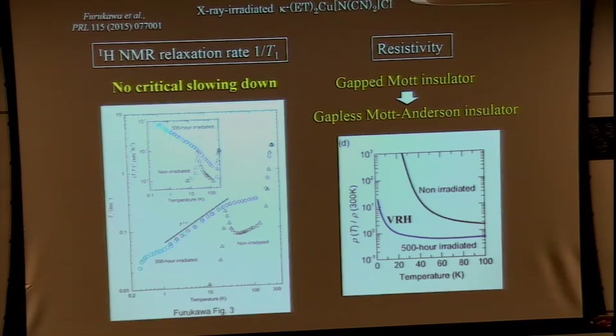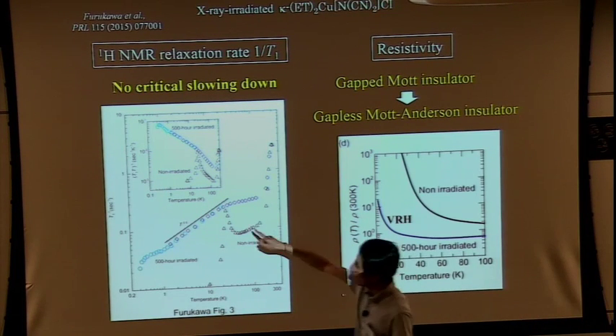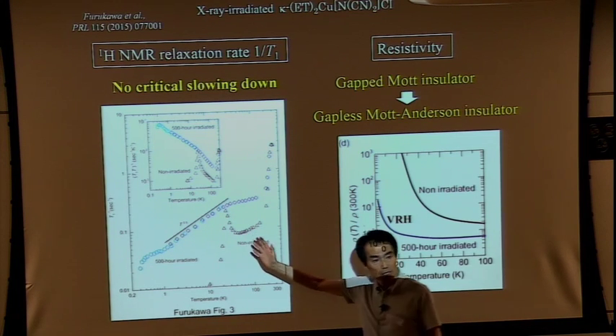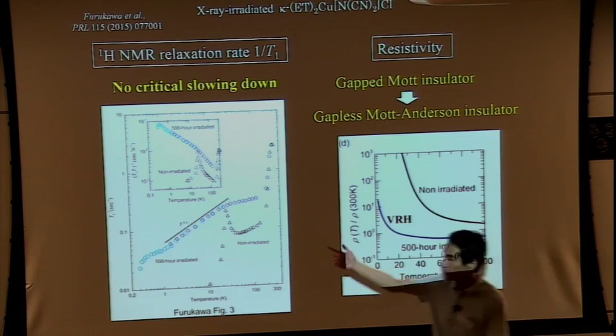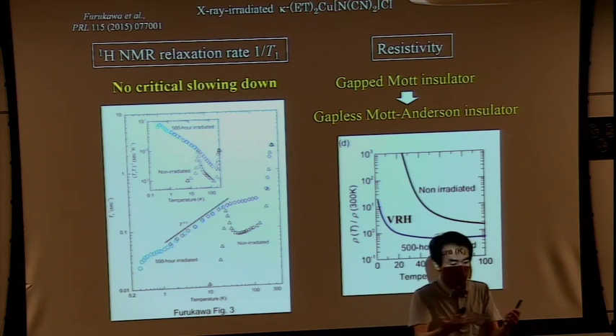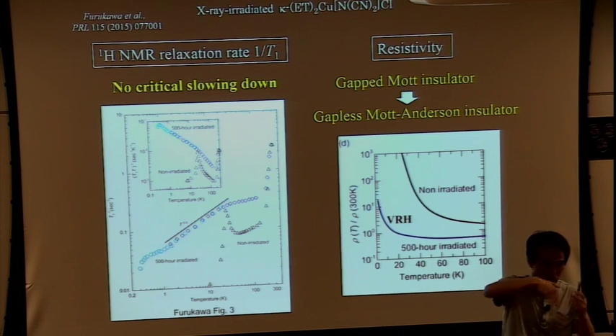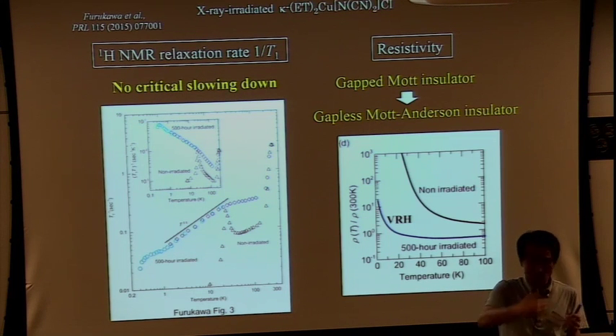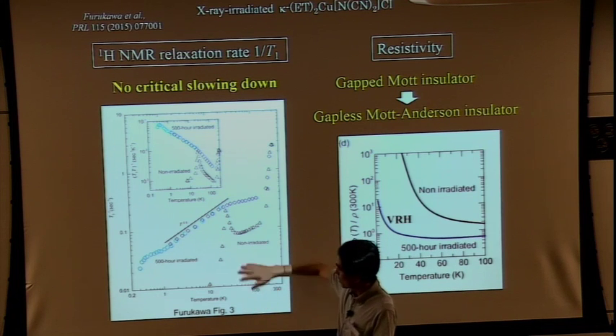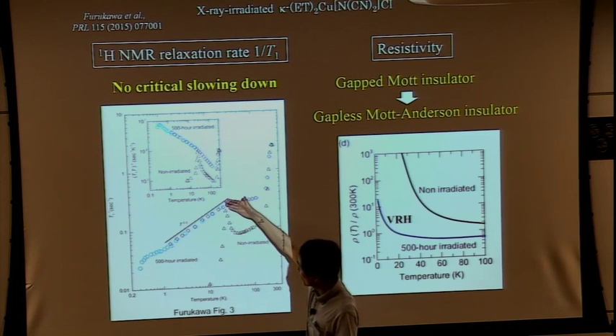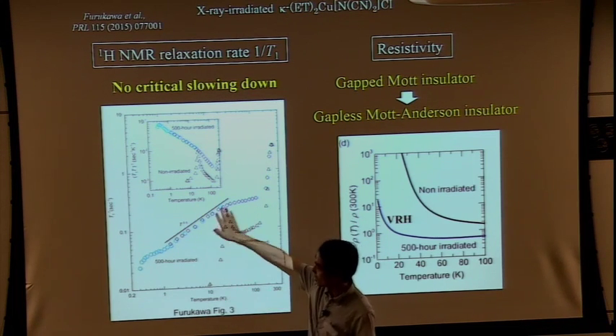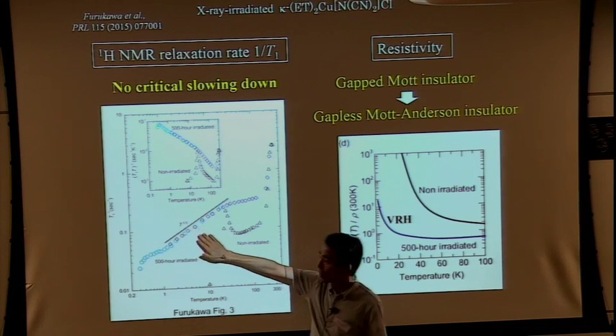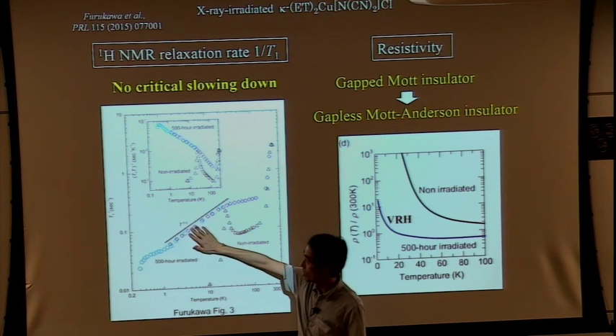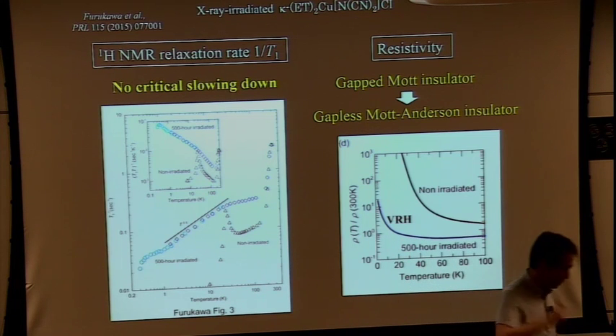And this is the NMR relaxation rate. Before irradiation, the 1/T1 shows a sharp peak. This is the clear manifestation of the antiferromagnetic ordering, because at high temperature spins are fluctuating, but when the spins are ordered, the motion of the spins is restricted, so only the spin wave or restricted spin excitation occurs. So the NMR relaxation rate shows a very sharp peak around magnetic ordering. But this peak is gone after the X-ray irradiation, and 1/T1 is proportional to T to the power of one half, the square root of the temperature. This temperature dependence resembles that of the pristine spin liquid. So we think that the spin liquid is generated from the classical magnet by introducing disorder.